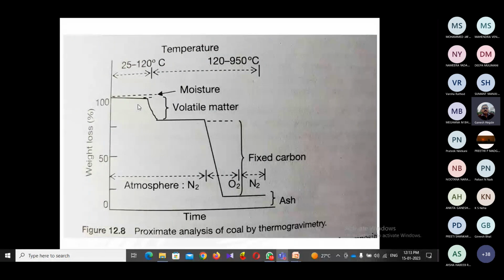Look at this. What is happening now? This is a TG curve. So this is the weight loss now, 100% sample. Okay, 100% means there is no weight loss. And as you keep on heating, like now it is shown here, 25 ambient temperature to 120 degrees Celsius. So what is happening? There is a slow decrease in the weight. What does it show? It shows moisture loss. Okay, so there is a moisture loss.